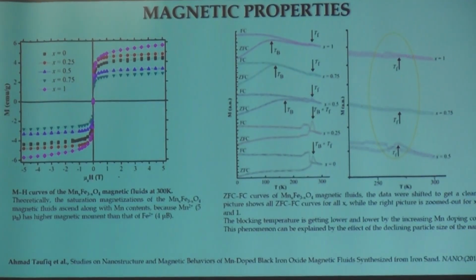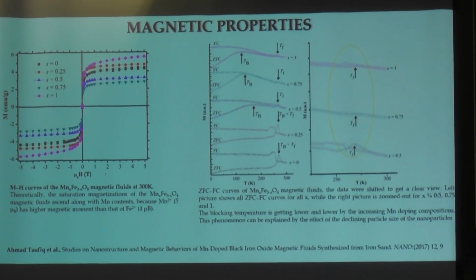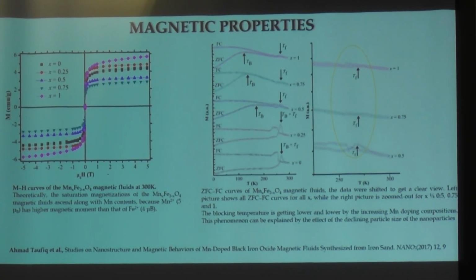What is the difference between powder and ferrofluid? The data is quite similar, but the magnetization is lower because the particle size is lower than the nanopowder and cluster. There are several effects, but we focus in here. In ferrofluid, in magnetic fluid, there are two data: freezing temperature and blocking temperature. In the powder, we have only one, the blocking temperature. But in the ferrofluid we have a freezing temperature. This originated from the liquid carrier and surfactant, so the freezing of the liquid carrier and surfactant. If we zoom out the data, it will be something like this. This data was also published in Nano.